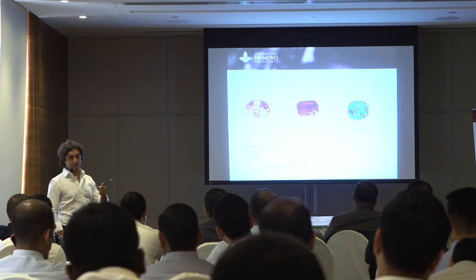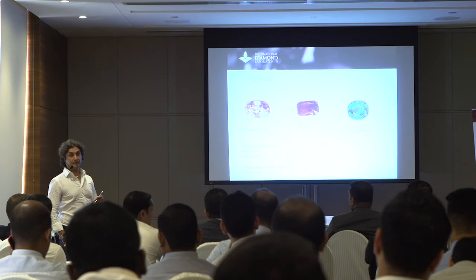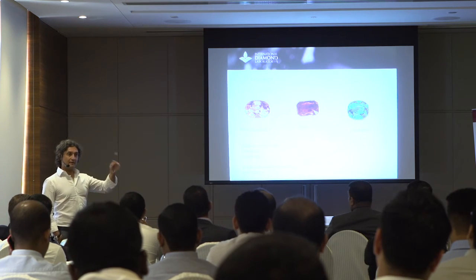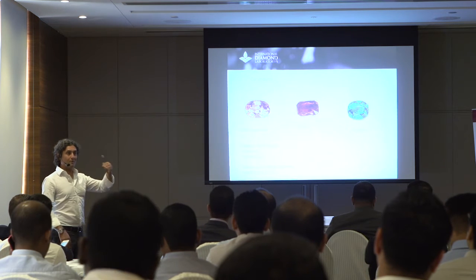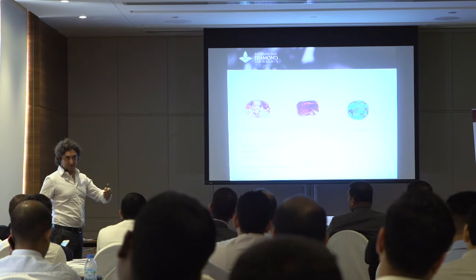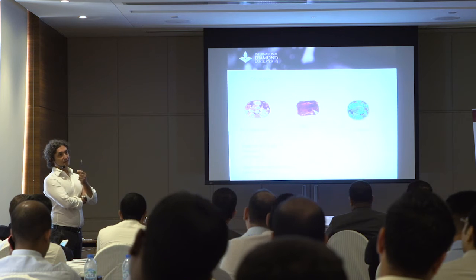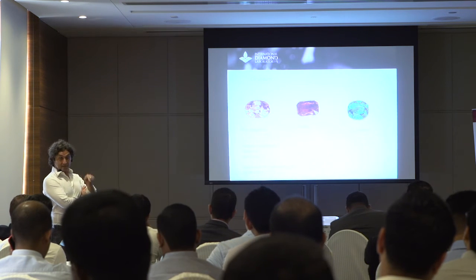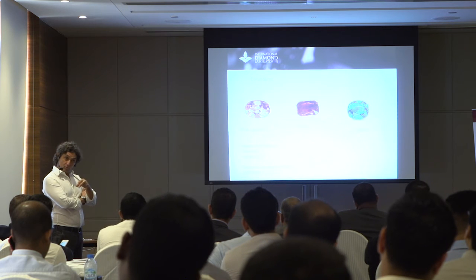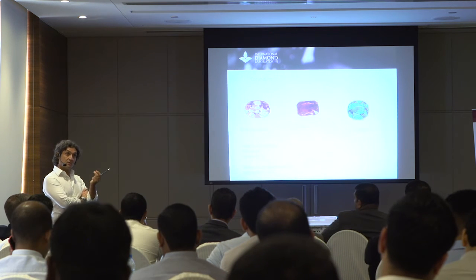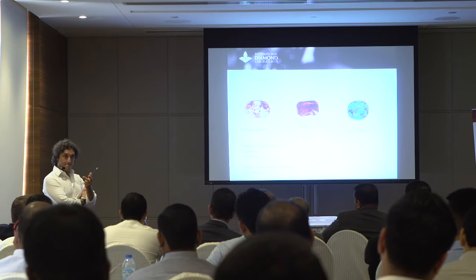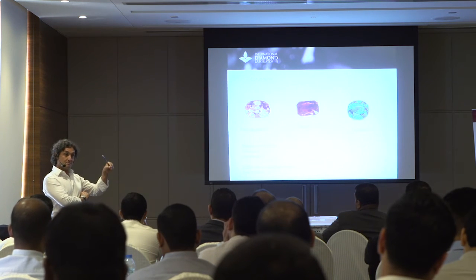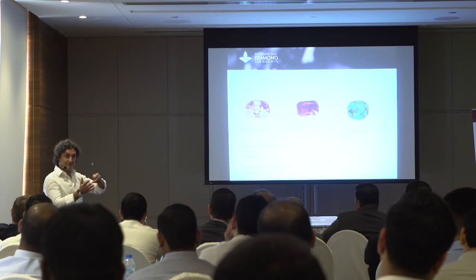Have you seen any of this type? The color and clarity treatment is the cobalt glass filling. So the regular glass filling is colorless. They use it on rubies. But they can make a white sapphire blue because they use a kind of blue glass. So you will see a blue stone which is color treated, plus it is glass filled because the glass is blue.